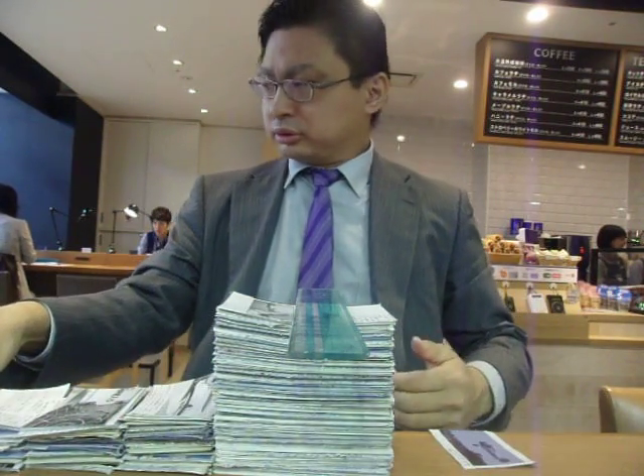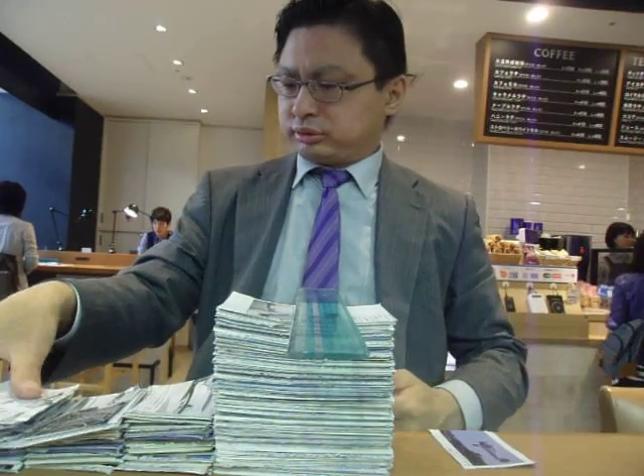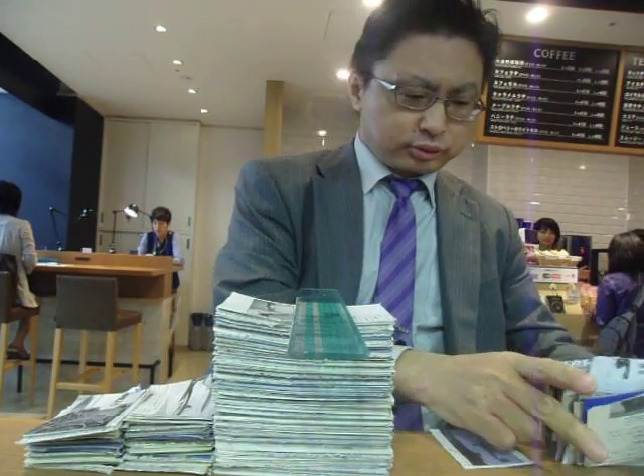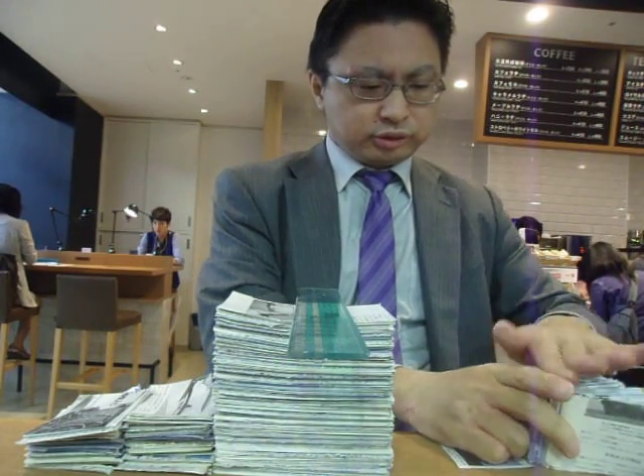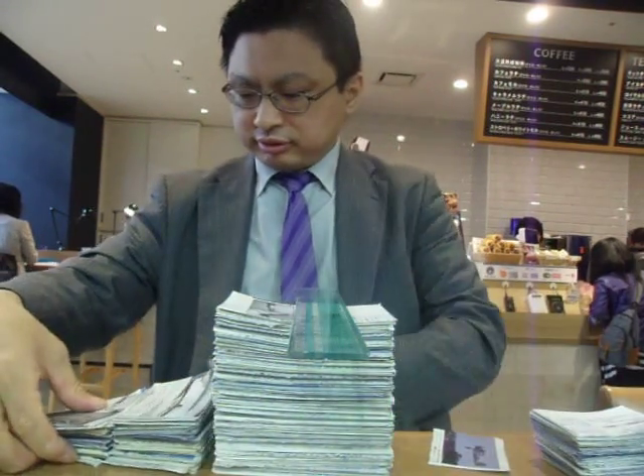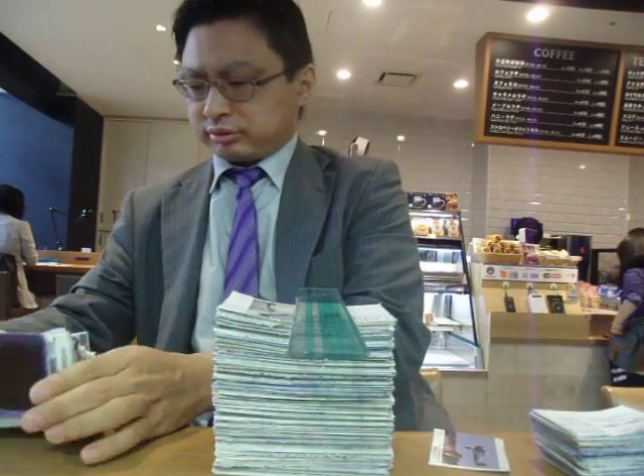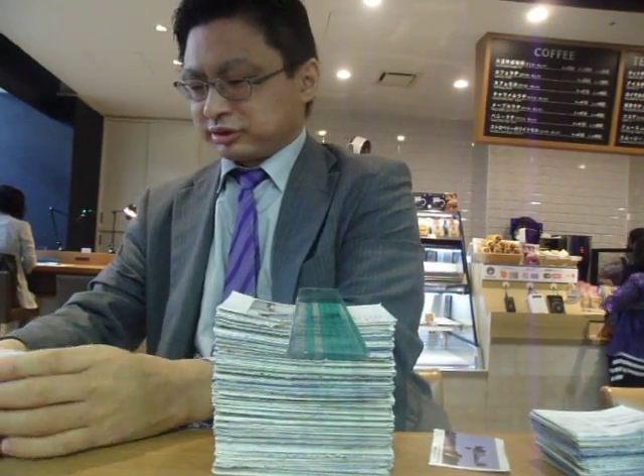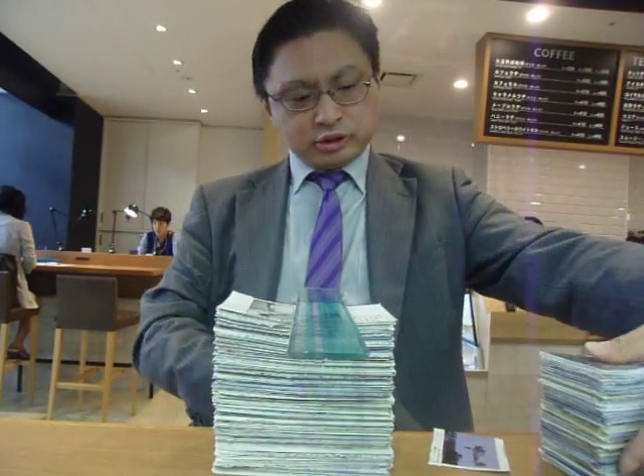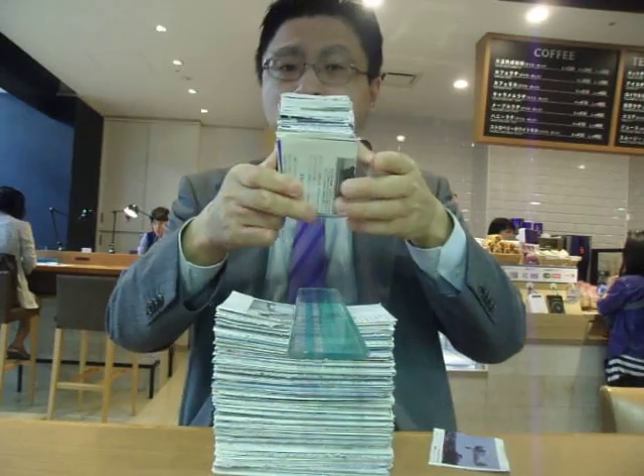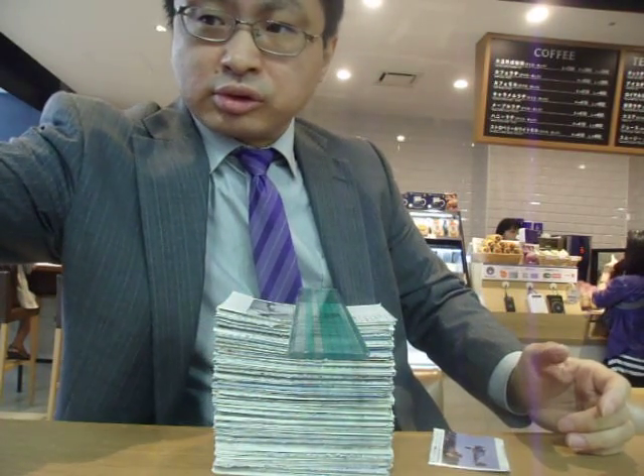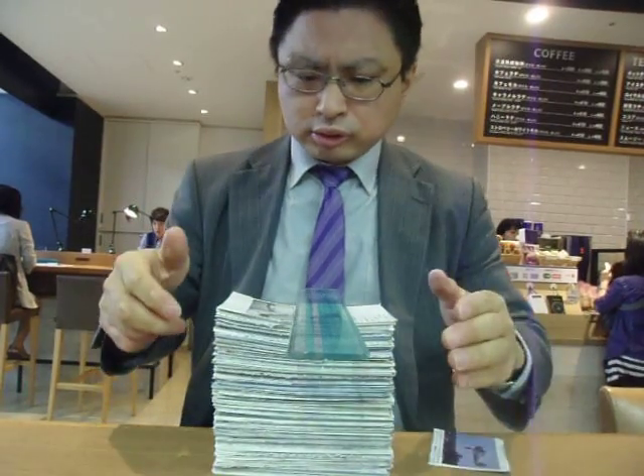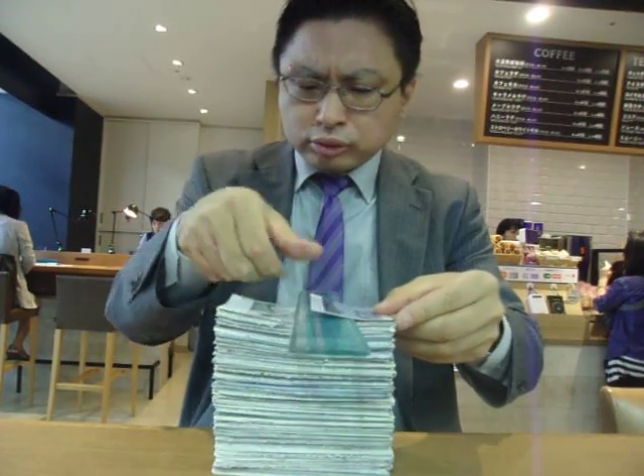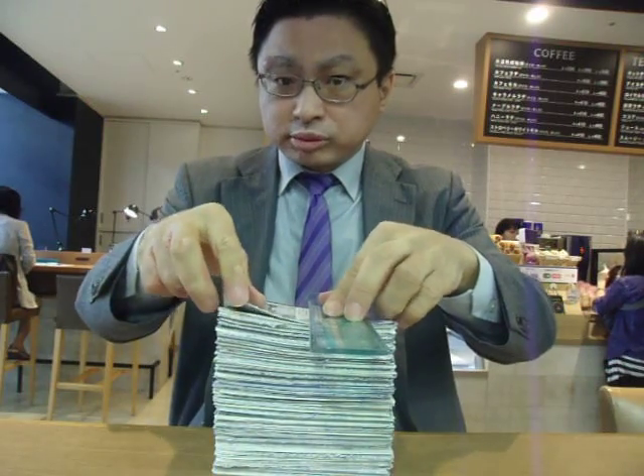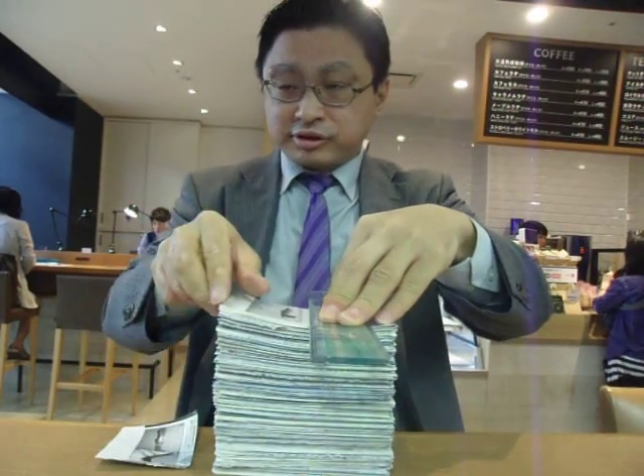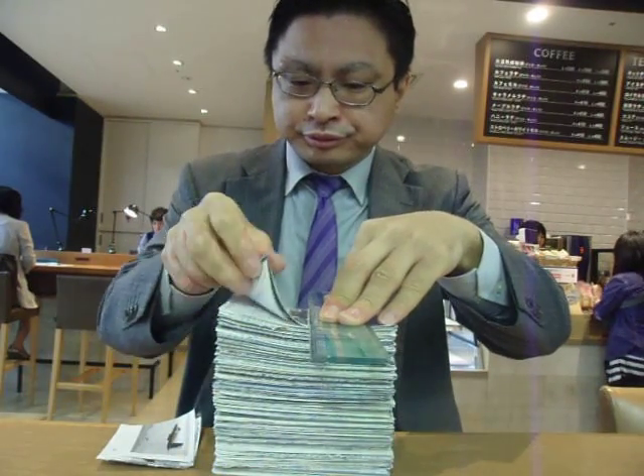And in order to address this, we actually grew a single crystal and then crushed it up. And we crushed it up so that we could compare to a powder sample that had never been grown as a single crystal. And then undertook a fairly careful crystallography study in which we compared the diffraction patterns at 15 Kelvin, so this is in a non-magnetic state, between the two samples. And what we were able to conclude is that the powder sample, which had never been grown as a crystal, has 0% stuffing, and the single crystals that have been crushed up have about 2.3% stuffing.